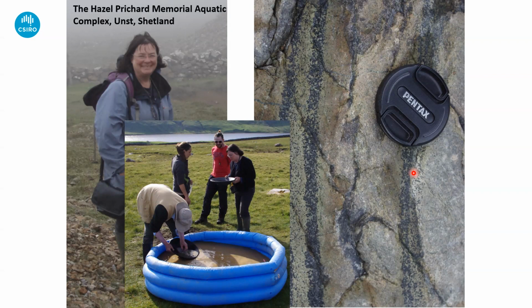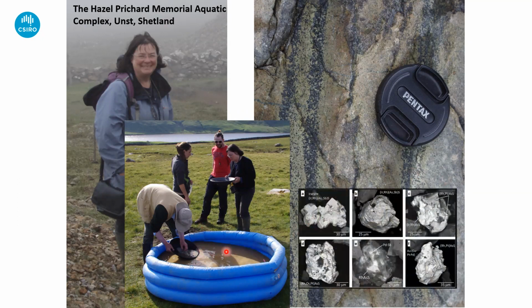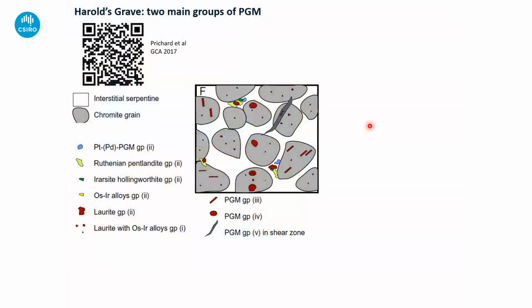So this is again going back to some work I did with Hazel. This is Hazel's unique sampling technique for getting platinum group mineral grains out of chromite seams. This is what we call the Hazel Prichard Memorial Aquatic Complex, which is an inflatable paddling pool on the side of a mountain on Unst. This is the Harold's Grave chromite. And what Hazel was doing was panning the drainage off this little outcrop to pull out platinum group grains, because you remember the Harold's Grave locality is the one where we get these astronomically high 10 ppm concentrations of iridium group metals, way higher than we see anywhere else.